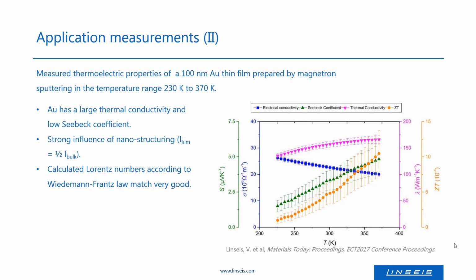The second measurement which is presented is a measurement of a 100 nanometer thin gold layer, as this impressively shows why thin film characterization is so important. Gold films are very often used in semiconducting industries as contact material or heat spreader.